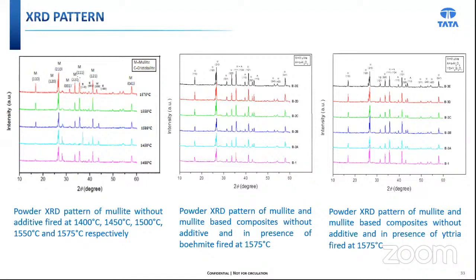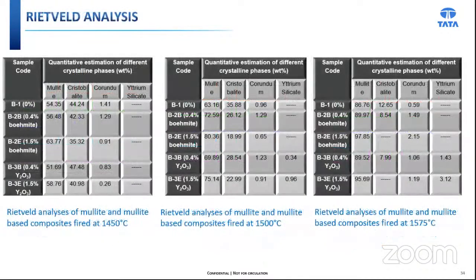Similarly, the same thing is applicable for the boehmite as well as the yttria addition, but for boehmite, some alpha alumina and corundum crystals have been observed. These are the results for the Rietveld analysis.